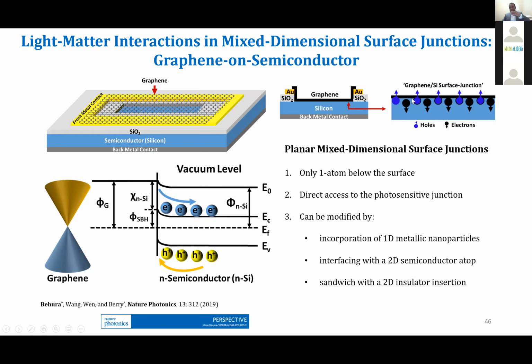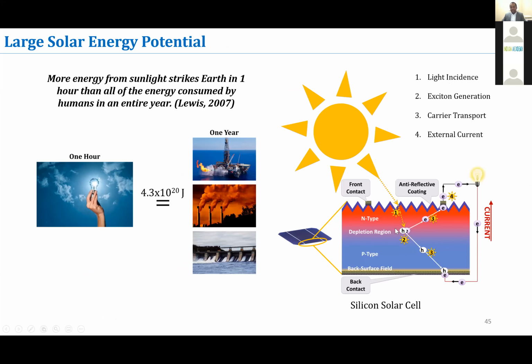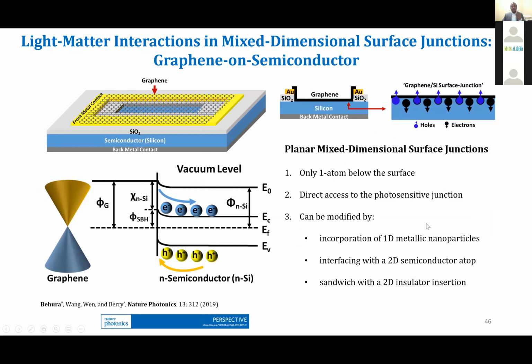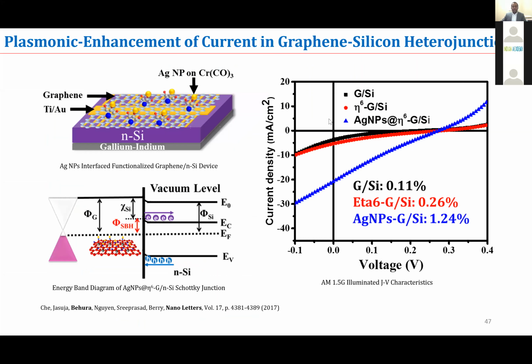And because the junction is close to the surface, the electric field can help the charge carriers to travel faster, unlike in a silicon solar cell where your junction is buried inside, and the electron has to travel all the way from here to the electrodes. So there is a probability that the electrons can recombine and be lost. By using this kind of technique, a 2D, 3D kind of junction, we can eliminate the recombinations. So inspired by that theory, we built graphene silicon junctions, and we also put several metal atoms on top to further enhance the light absorption, and we were able to enhance the current in a graphene silicon type of junction.